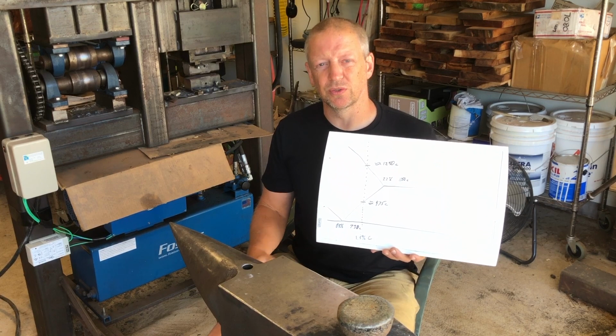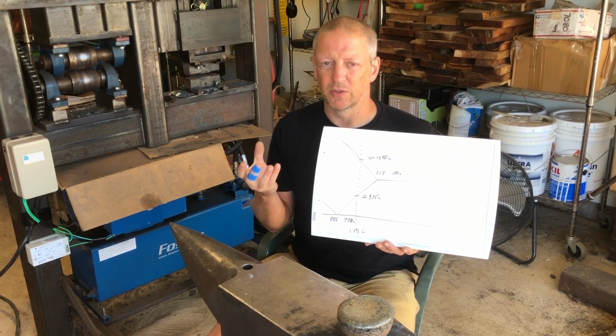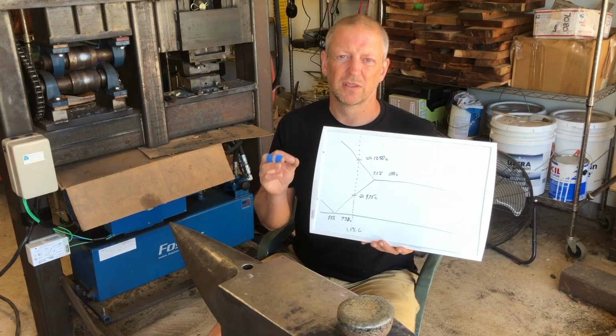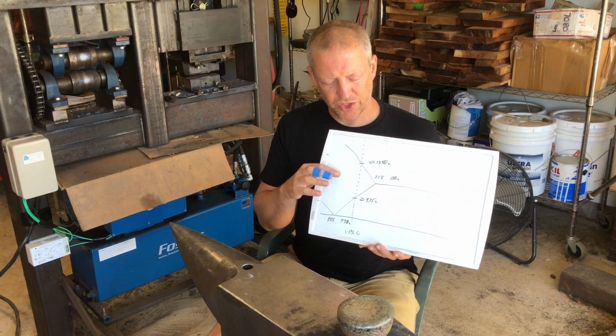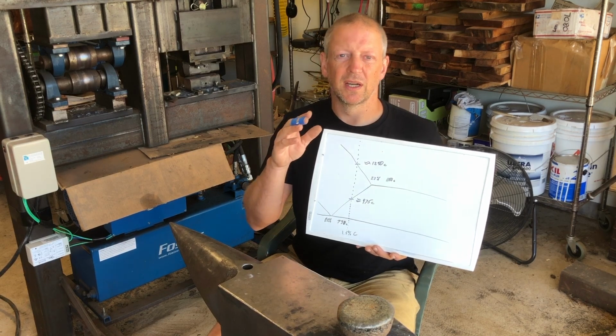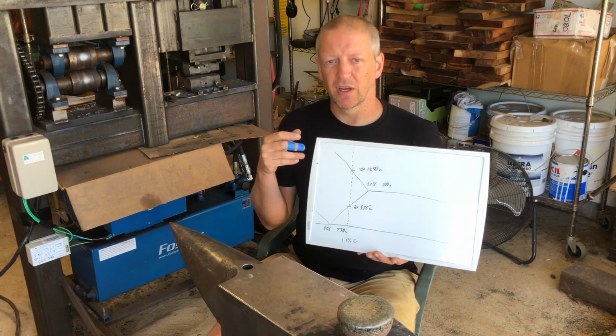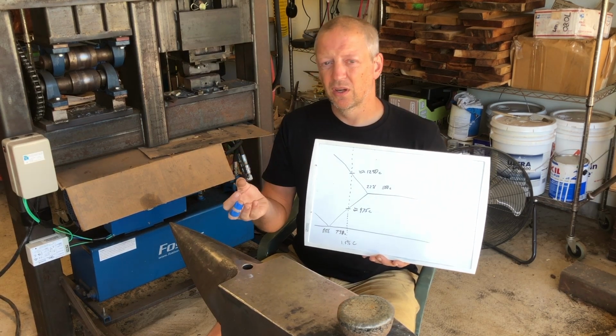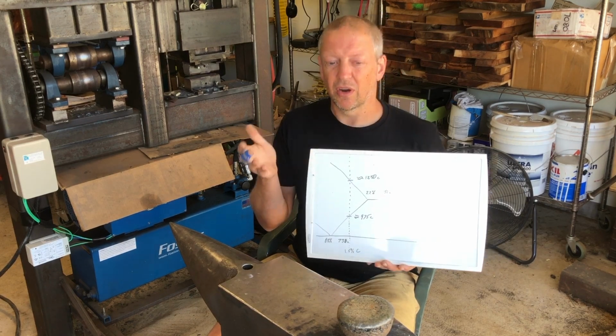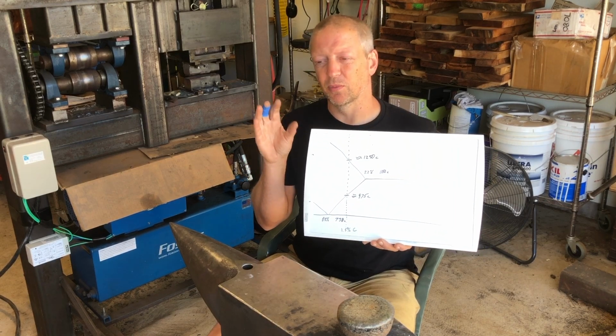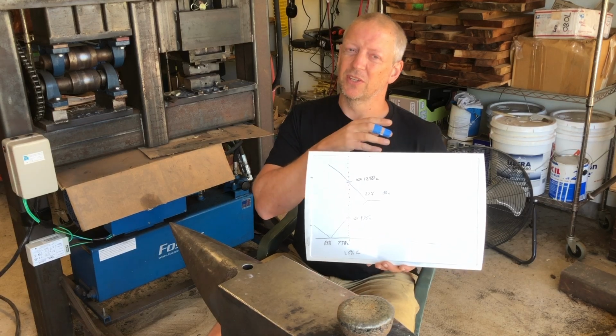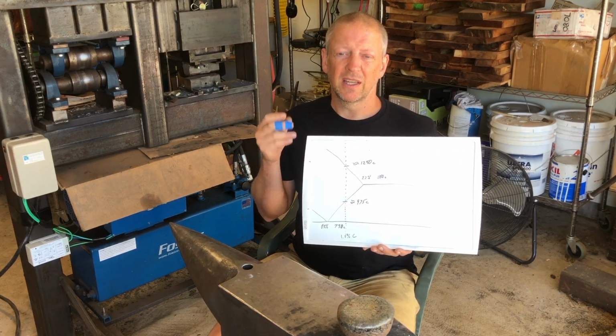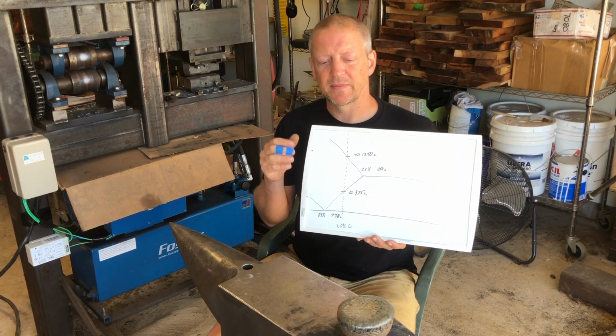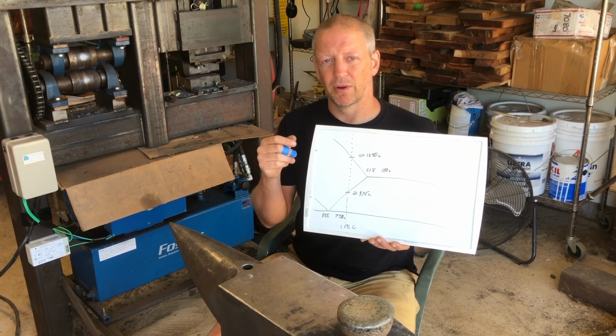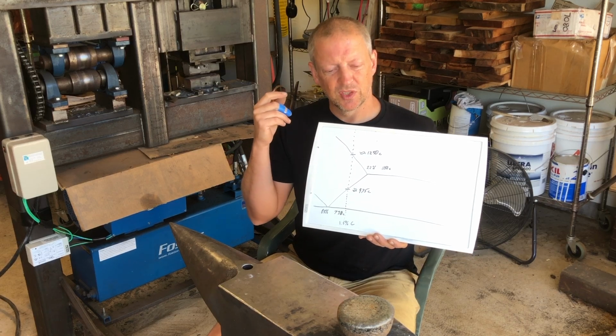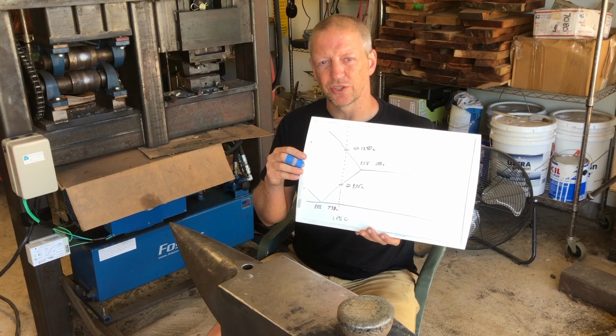Regardless of exactly what temperature you choose to roast at, one thing that almost certainly will happen is you're going to change the grain structure of your ingot. And that change in grain structure helps lead to better forging. Now, I have done roasts from half hour all the way up to 3 hours. There are definite differences in there. At a half hour, there was more forging difficulty than at 3 hours. That doesn't mean you need to go to 3 hours. And depending on what your ingot is like, half hour might be perfectly sufficient. However, I do suggest doing some kind of roast before you start forging, so that you've changed that initial grain structure at the very least.